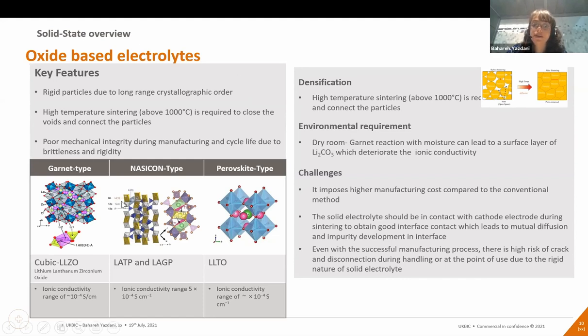So as you see, on their own, they have huge challenges, and the environmental condition is also similar to some cathode material, which is already in the market, moisture sensitive, which increases the cost. So this is an existing challenge as well. But the new challenge is that they require high temperature for sintering, and they should also be compatible with different cathode materials. And as I mentioned, even with successful manufacturing, there is high risk of cracks and disconnection during handling. So there is a huge area of research needed for these very safe materials compared to the liquid-based electrolyte, to deliver them to the market and meet expectations, including hybridizing them with polymers or with other chemistries to tackle their challenges.